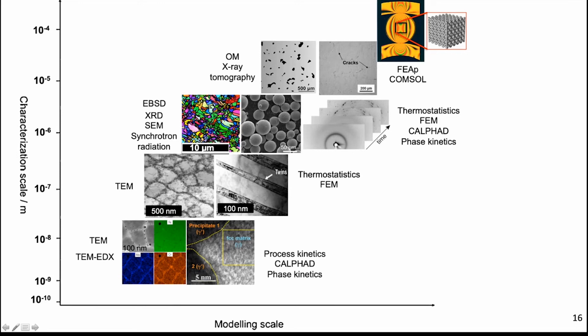For instance, the finite element analysis allows me to describe at the sub-micron scale or the micron scale. COMSOL is one such software. But I can use the so-called thermostatistical theory, or CALPHAD, which is computational thermodynamics, to tailor the presence of grains, or the finite element method to go up in scale and understand how all this interacts at the macroscopic scale. And also the precipitation and the segregation. There is kinetic software, phase kinetics, that I can use.